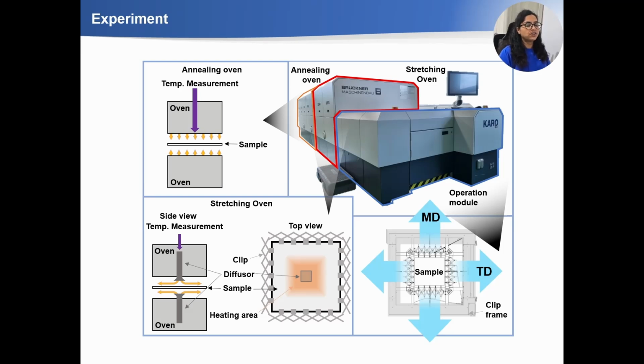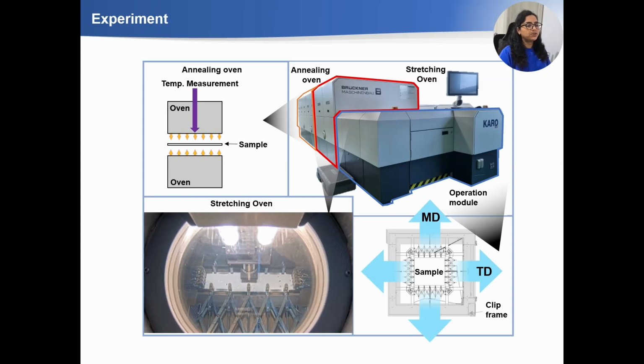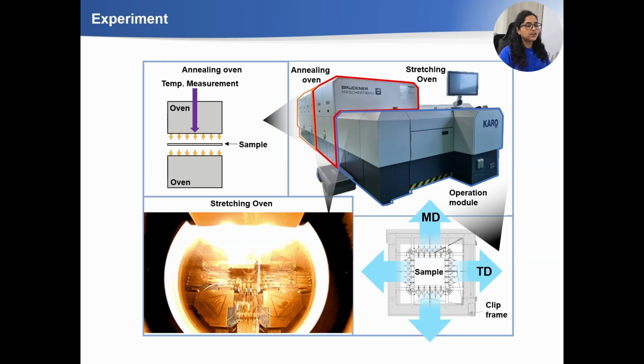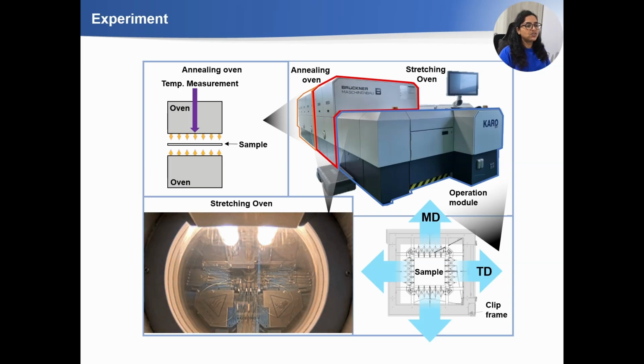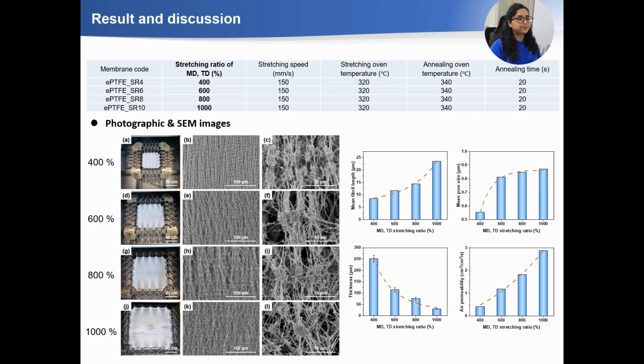and we change the different types of stretching parameters to get uniform thickness and micropore size of the material, to use it in different kinds of applications. Here you can see we put the PTFE sample inside the chamber, and with different kinds of parameters it gets stretched, and we get a uniform thickness stretched membrane.